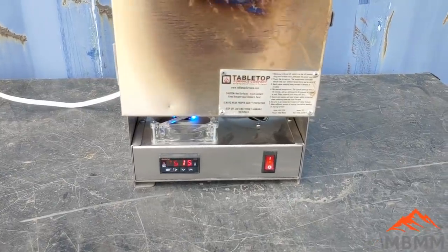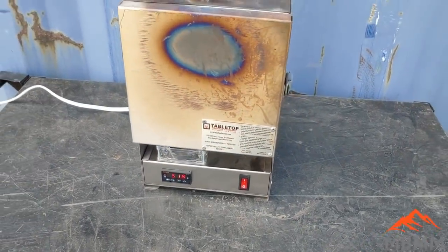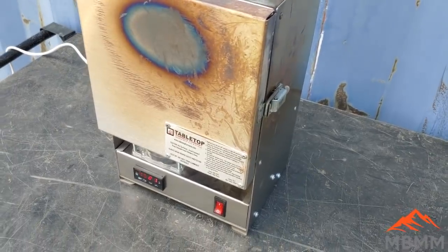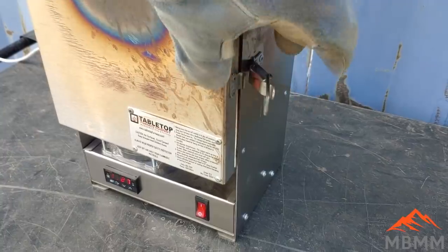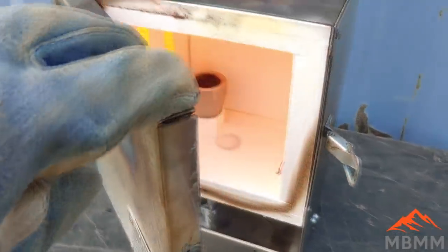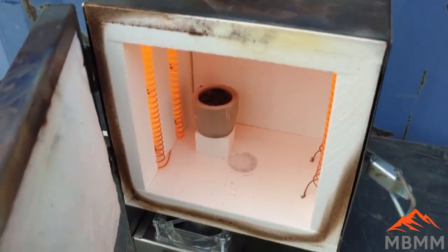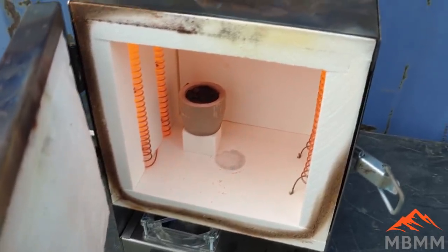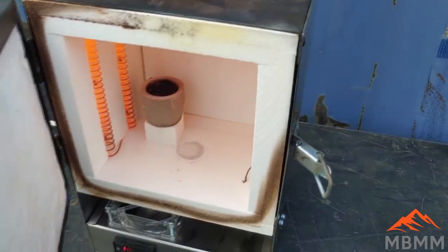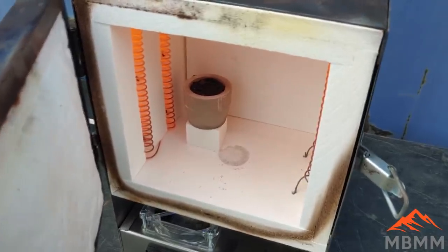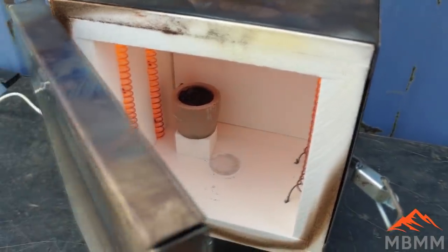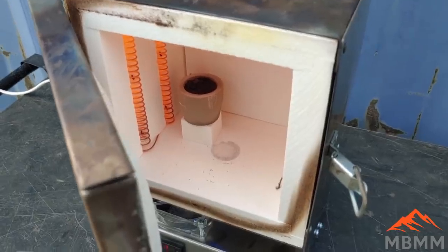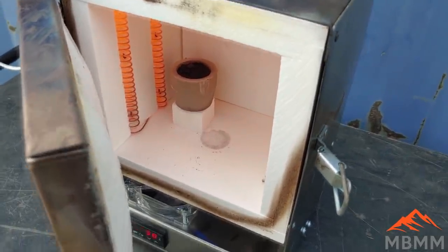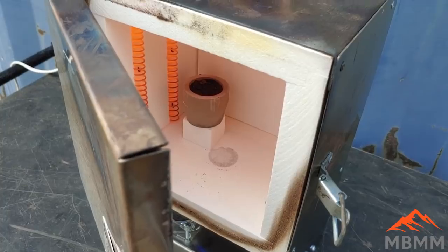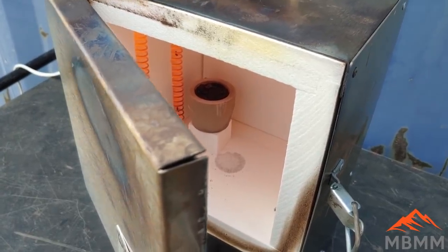All right, we're a little over 1500 degrees, and it's been about 6 or 8 minutes. It hasn't been very long. So let's see if I can unclamp this thing with one hand. Our lead's molten, and the black stuff on top is either a little bit of slag or lead oxide. The temperature inside the furnace is 1500. That cupel probably isn't up to temperature yet. So we'll check back on it in a couple more minutes and see if we can see that lead starting to oxidize and drive into the cupel.